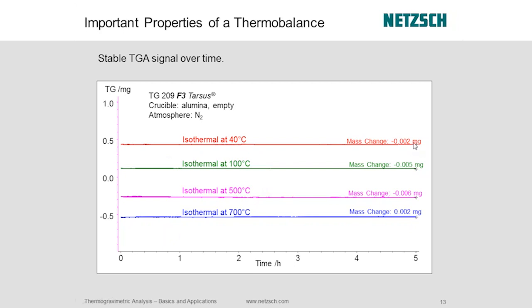You're down in the range of below 10 micrograms for the most part, 2 micrograms here, and at the highest temperature recorded here, 700 degrees, 2 micrograms. So it's really tremendous stability. It's important because if you've got small mass changes and your signal is not stable, then you may lose those mass changes in the noise of the signal. So you want a very stable thermobalance. And no matter what TGA you're using, you need to see some kind of performance criteria like this. Okay?